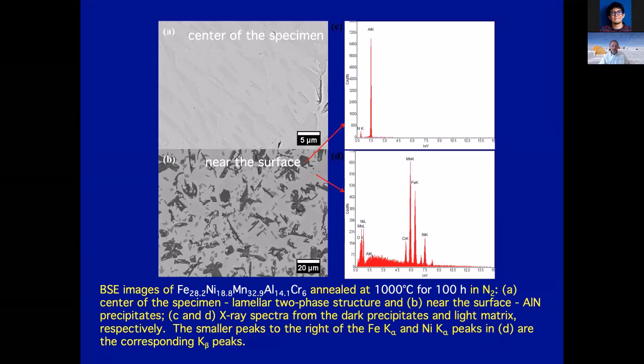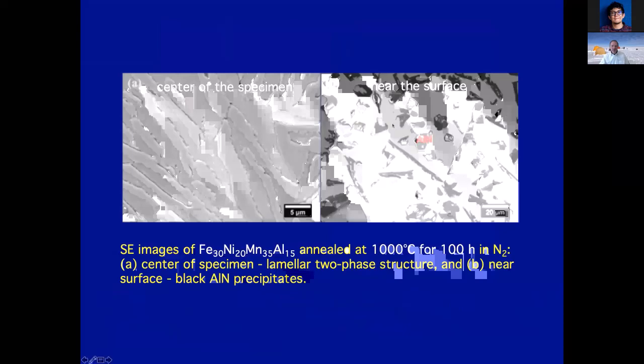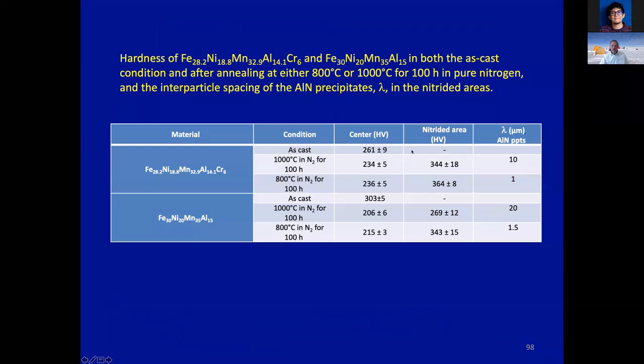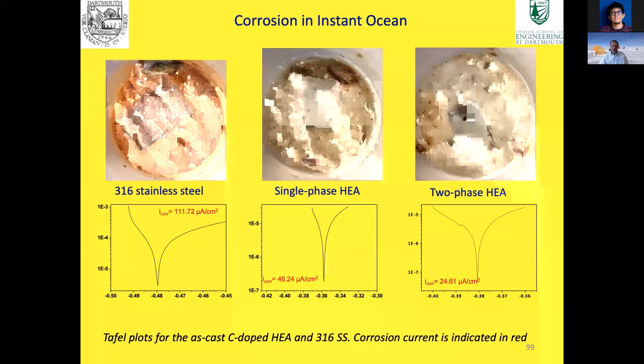So this is the chromium doped material, and this is the material without chromium. Again, you can see the aluminum nitrides. And what that does to mechanical properties: in the center of the specimen, we get a hardness that looks like this, and at the surface, we get a much greater hardness in the material. So you can actually case harden these materials by nitriding them. And so the last couple of things I just wanted to mention are a couple of very preliminary studies we've done. Because we have these materials and they look a bit like stainless steels, we decided to compare the corrosion to that of stainless steels.